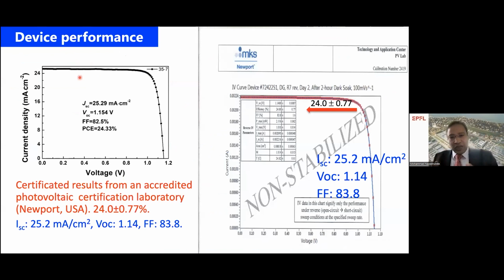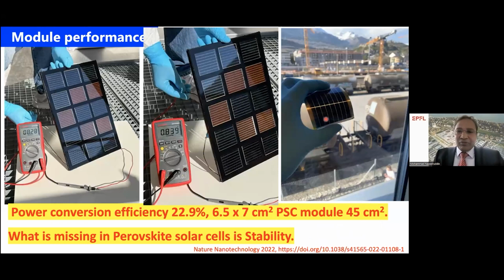Now, using this type of configuration in NIP, we have obtained over 24% efficiency, and this efficiency was certified at Newport. The values exactly tally between our lab's values and the values obtained at Newport, showing that our measuring system is consistent with international standards. And now I come to what we can do further.